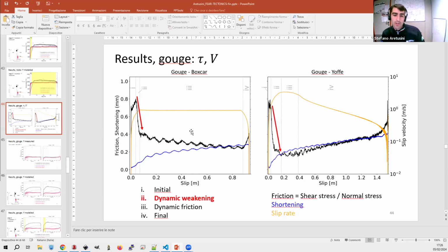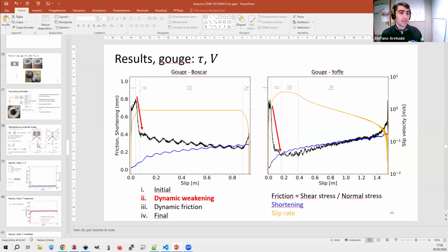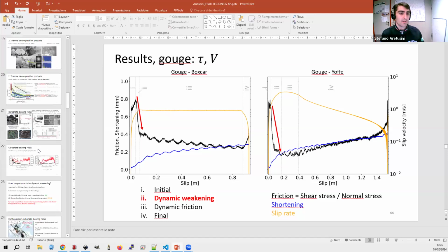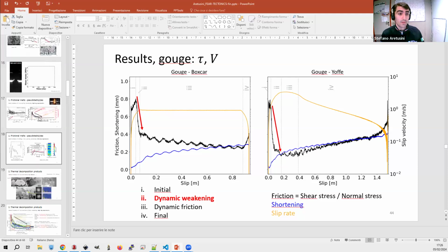We tried in only two or three experiments to include more fibers in several positions, one very close to the shearing surface and one a few millimeters away. And we could really see that the heat was localized. This is typically the case also in the data from the literature that I showed, even if it's on a different type of rock and associated with melting of rocks.